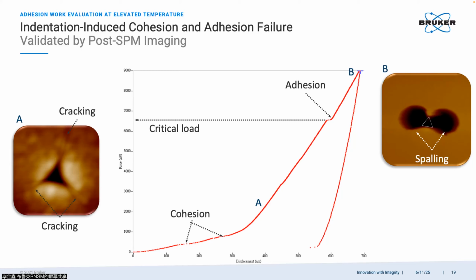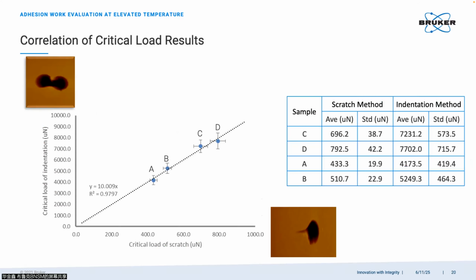So we have two methods, or two metrologies, for interfacial bonding measurements. One is indentation, the other one is scratch. And for a lot of cases, these two different metrologies can have a very good linear or proportional behavior between them. You can see we have four different interfaces from strong to weak. We applied the indentation to induce the delamination and pick up the critical force for the indentation method. We are also able to perform the scratch test and pick up the critical load.